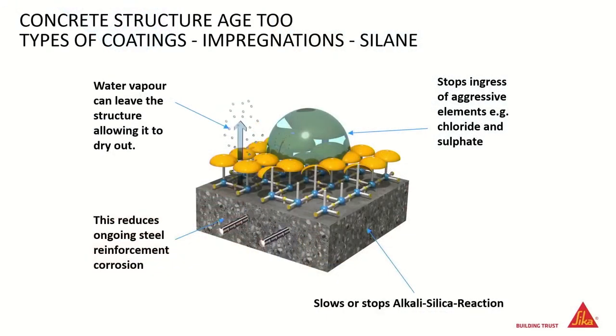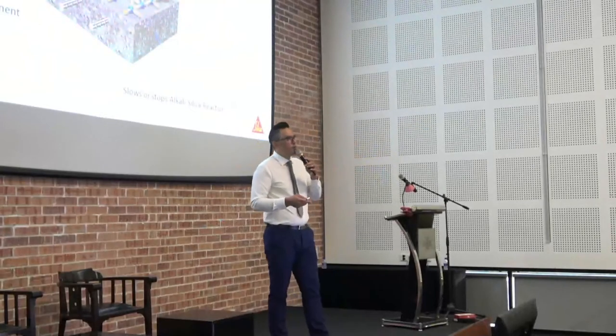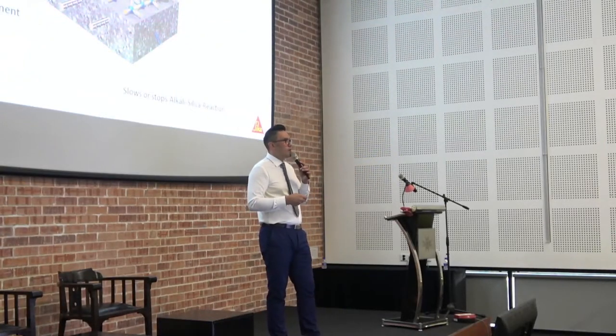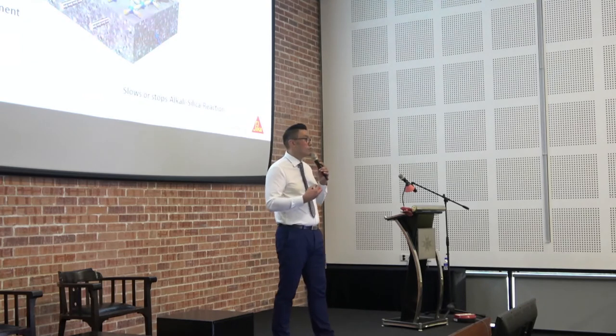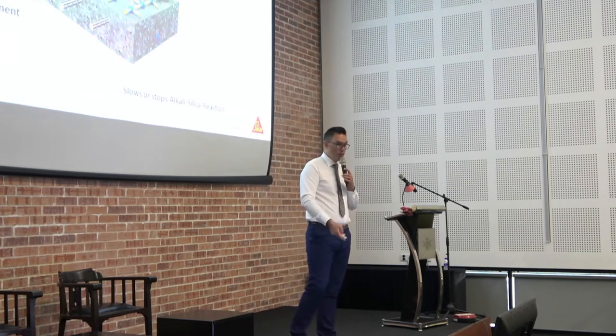With the impregnations, the water can leave the structure, allowing it to dry out, and you also reach your designed concrete strength faster by drying out. When you take the moisture out, it also slows or stops a phenomenon called the alkali silica reaction. You need moisture for it, and depending on the aggregates inside the concrete, you might end up with this reaction, which is an expansive reaction and can crack your concrete.